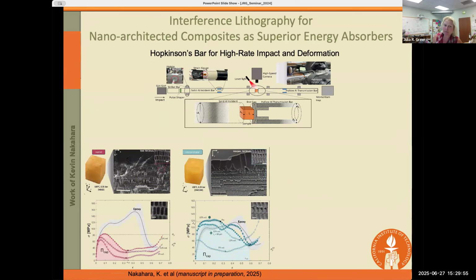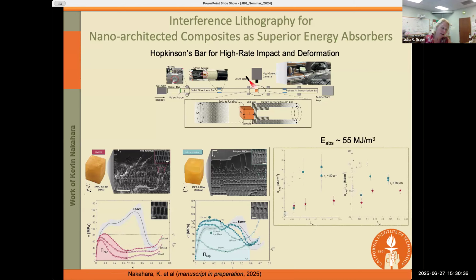And what we're observing is that, for example, the layered composites, something that we would expect, like a layered cake, quite literally, something that we would expect to collapse in a layer by layer fashion and therefore offer greater energy absorption, doesn't actually offer that. Instead, we're seeing much amplification in terms of energy absorption when the composite is interpenetrated. And that now makes sense because now we have this energy transfer mechanism and the load redistribution mechanism available to us when the nano-architected components are able to more efficiently redistribute the stress that they're experiencing. So this was a very important learning for us because we're showing the way of how these nano-architected composites can be utilized in real personnel protection applications, for example.